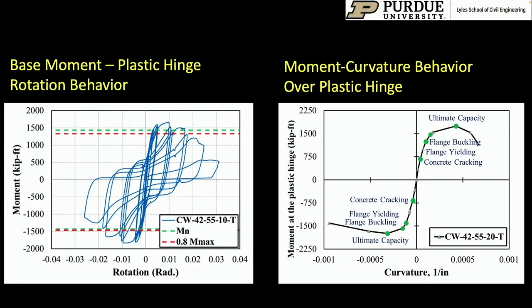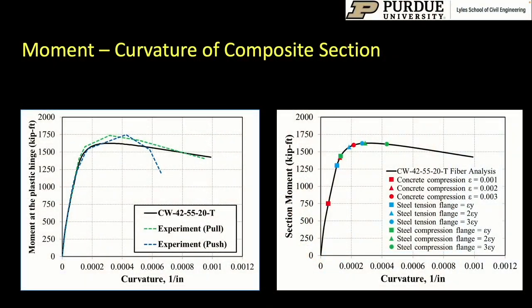Taking this experimental data, we were able to develop the plastic hinge versus rotation response. This is the moment versus base rotation or the plastic hinge rotation response. And the backbone of that is shown right here, along with the occurrence of various events which tell us more about the behavior of this specimen, and in particular how the ultimate capacity is being reached. And what we found was that the recommendations for stiffness and strength compared very well with the experimental data. For example, I'm showing you here the experimentally measured moment curvature response, which is shown with these dotted lines, and the solid black line is a simple fiber analysis of the cross-section, which compares very well with the experimental data.